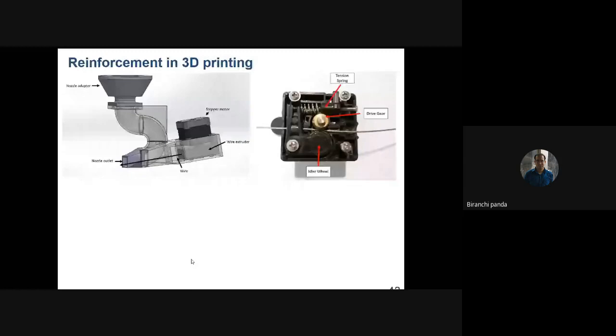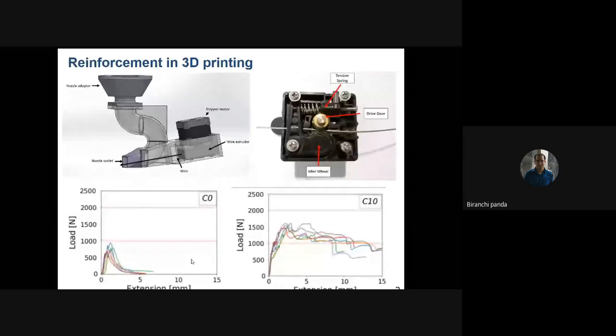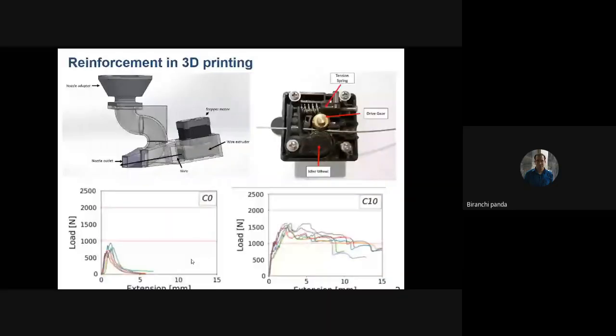Now the main challenge is reinforcement during 3D printing. We know that concrete is a brittle material, and we need to improve its ductility. For that reason, we tried to find a nozzle design that can place the reinforcement, the steel cable in this case, during printing. This nozzle deposits the steel cable along with the material during printing. Once we printed this material, we got a very good result in terms of the load versus extension curve. So we are trying to reinforce our material with this kind of steel cable.